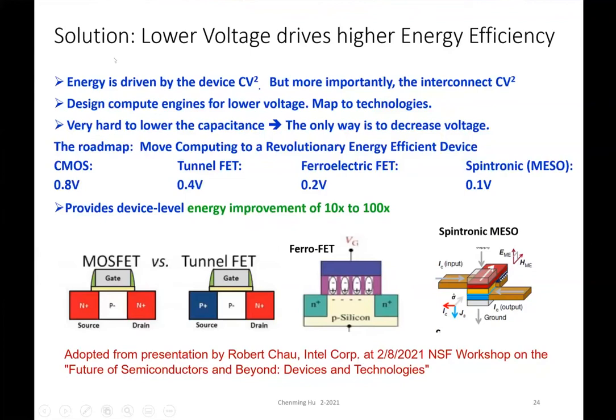He said, solution is lower voltages drive higher energy efficiency. We just have to make transistors operate at lower voltages. And he says CMOS 0.8 volt, people are using 0.7 volt, and now tunnel FET can go to 0.4 volt, ferroelectric FET can go to 0.2 volt, and this is the one I'm going to show you another slide later. Spintronics can get to 0.1 volt, although the speed is not as good as the ferroelectric FET and the CMOS.